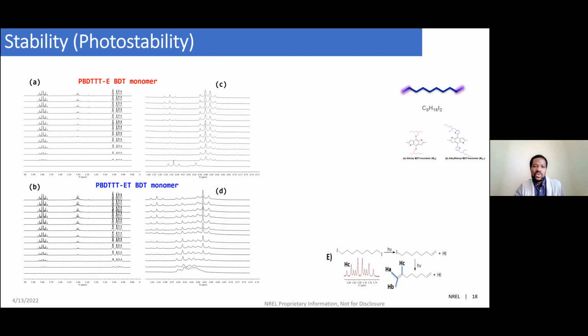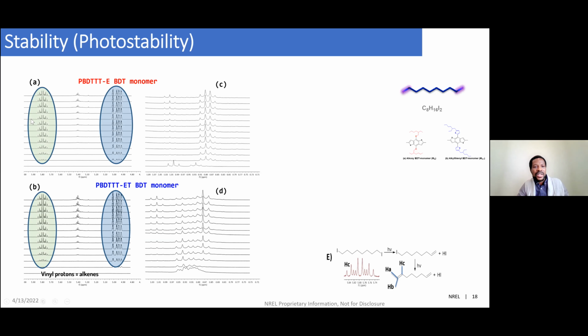And what we did is to have this monomer in solution and illuminate it over time. And here you can see the spectra from the initial position, and as we illuminate them every 10 minutes, we measured. Clearly, in the chemical shift from 4.8 to 6 ppm of the monomer, it's small, but you can follow it. In the presence of DIO, we have appearance of new peaks just after the initial exposure, from 10 minutes up to 120 minutes, with each peak increasing in intensity over time.